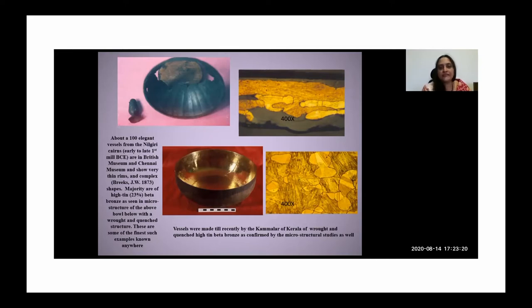Just to point out at the bottom, that brilliant vessel that you're seeing with the golden color inside and the darker skin outside is made more recently in one of those workshops that I was pointing to, by the Kammalar. At the bottom of it, you can see this ingot of about 15 centimeters, and then it's been forged through these cycles of hot forging and annealing into this very big vessel. And just next to it, you can see a microstructure.